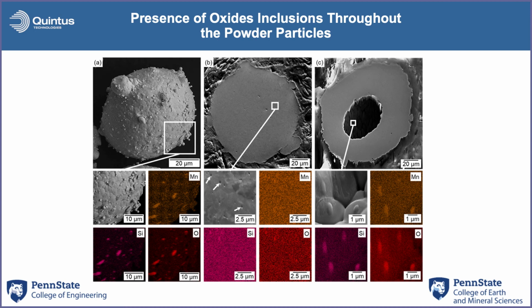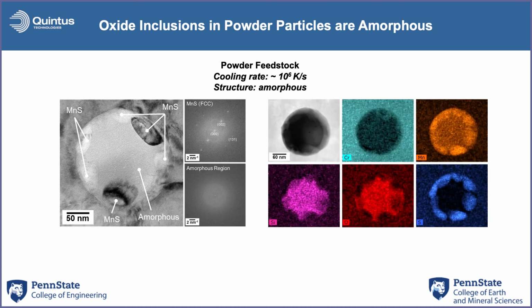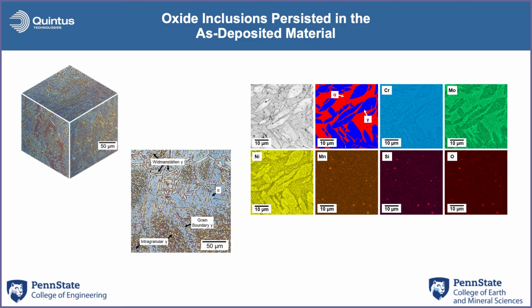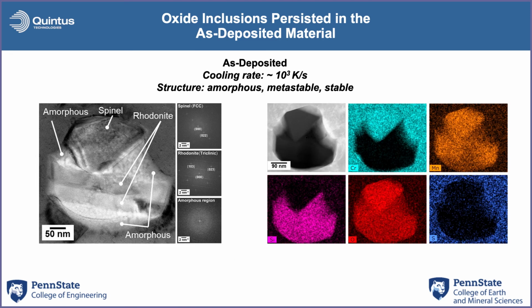We started looking at duplex stainless steel and austenitic powders themselves, taking them and putting them in a transmission electron microscope. We found that there are oxide particles in there, but they're spherical and amorphous, and that's not just on the surface. The stock answer for most people is, well, you're not handling your powder properly, you're picking up oxygen. Well, we're handling the powder properly, but we're actually cutting and cross-sectioning the powder particles, giving us the ability to see inside the particle, and we find these oxide inclusions there as well.